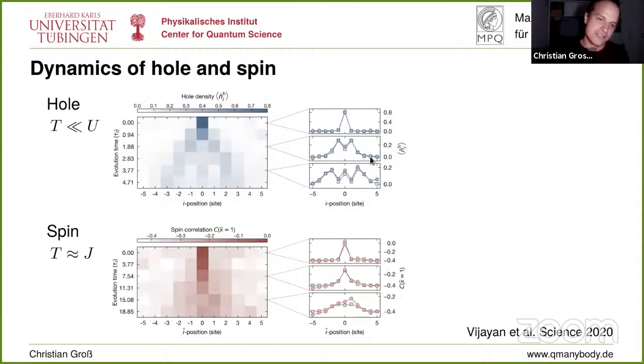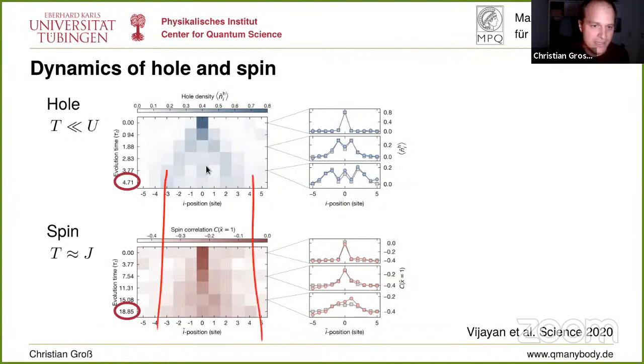And here you see basically what we get. In blue you see the density signal, and in red you see the spin signal. Let me not tell you much more now on this, but just highlight these times. First you see, to spread out to like 3 sites distance here, we need 4 hopping times, or 4.71 and 18.85. You see the spin is much slower.